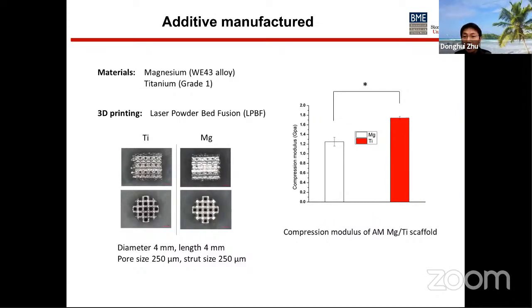So the material is magnesium WE43 alloy, and the benchmark control is titanium grade 1 medical titanium. We used the laser powder bed fusion approach for 3D printing.